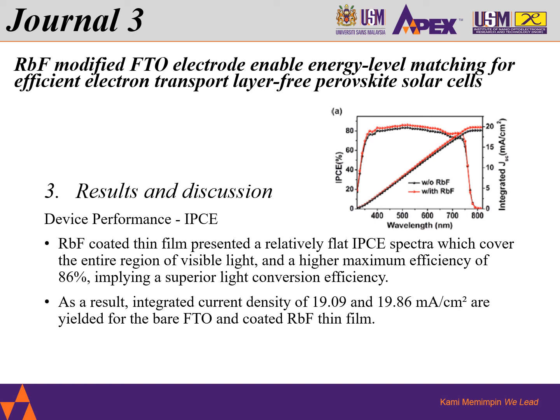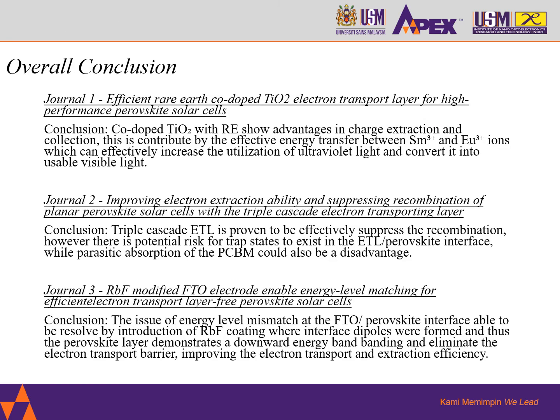But if you look at the integrated current density, the one with coated RBF is definitely showing a better current density, which is 19.86, compared to the one without, which is only 19.09. So now we are about to conclude what we have learned from the three journals.